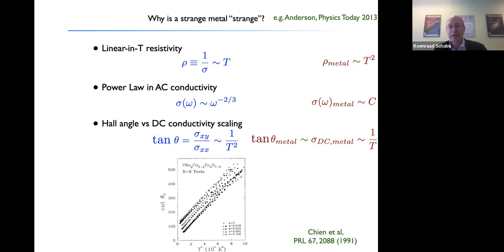Another famous example is the Hall angle versus DC conductivity scaling. In an ordinary metal, you can show that the ratio of the Hall conductivity to the ordinary conductivity must scale the same way. It's governed by the same relaxation rate as the DC conductivity in an ordinary metal. So this should go as 1 over the temperature if the linear in T resistivity is true. However, in a strange metal, you see that it scales as 1 over T squared, unlike an ordinary metal. Well, the two cannot be true at the same time. So this is a puzzle that one needs to explain.